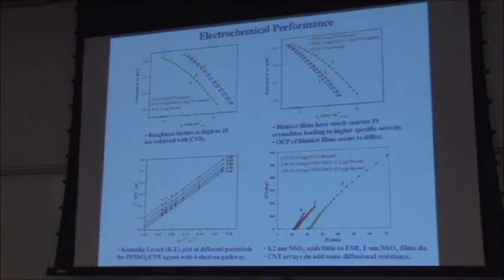So when we looked at the electrochemical performance, if you look at the kinetic activity, obviously the carbon nanotubes with the platinum will perform better than the platinum just on the Inconel, simply because there's more surface area. And you could see right away that the niobium oxide layer does ever so slightly degrade the ORR performance. If you normalize everything by surface area, so if you look at the specific activities, actually the coarser platinum on the planar supports as expected does a lot better electrochemically than the platinum on the carbon nanotubes. But again, you still get pretty good performance, and you get a slight reduction in activity with the introduction of the niobium oxide layer. If you look at the Koutecky-Levich plots, you have a 4-electron pathway.